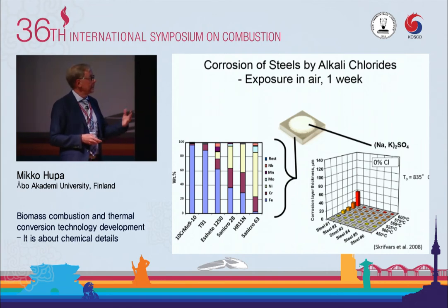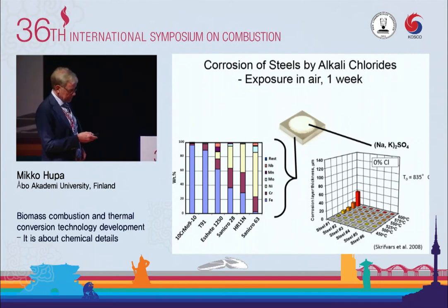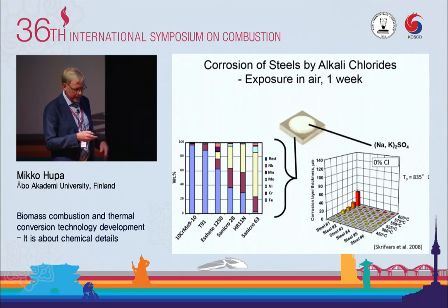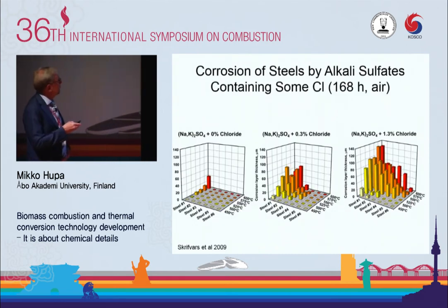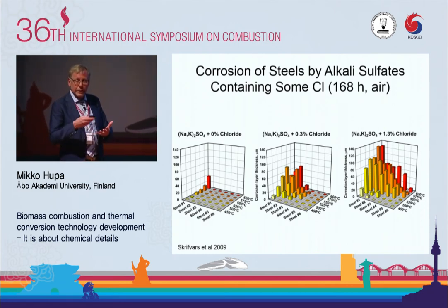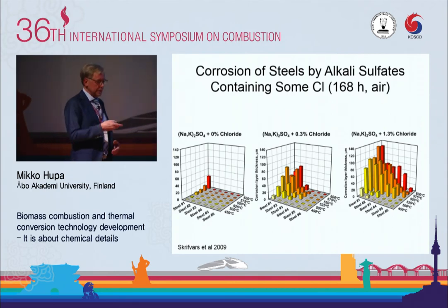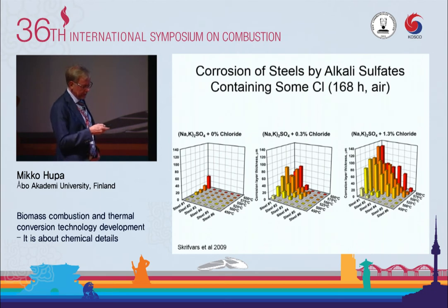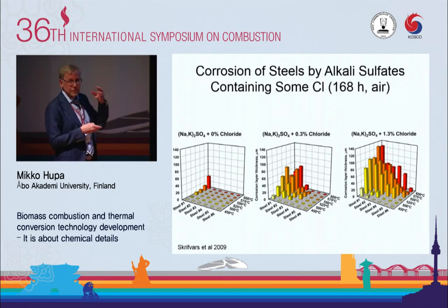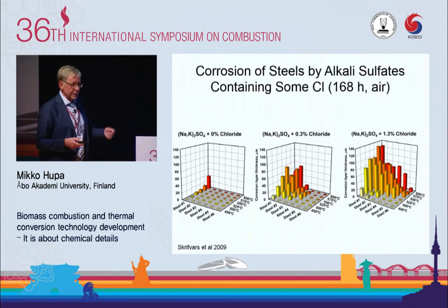That would be very welcome because then we would be able to go to higher steam temperatures. However, when we start mixing small amounts of chlorides into this system, this is the one I showed you, we put 0.3% chloride. We did it by putting sodium chloride or potassium chloride into this sulfate, melted it in advance, cooled it and crushed it. So the chloride was very homogeneously mixed. And you see that now most of these materials already start showing heavy corrosion. These are high numbers. These are micrometers per week. And this is already visible by eye in that short time. And when we have 1.3% chloride, even the most expensive materials started showing clear corrosion at 525, explaining how this is really the obstacle to going to higher steam temperatures.